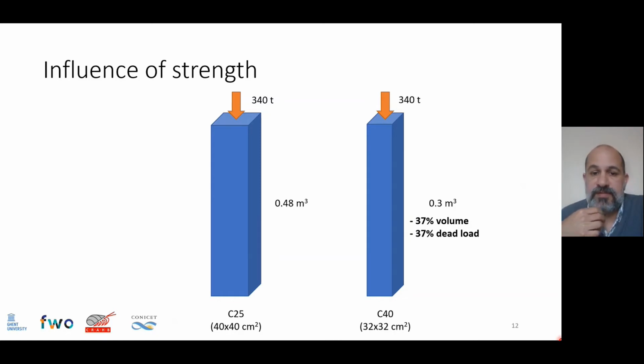So let's take this example, a column made with concrete with strength class 25 megapascals. We would need half a cubic meter to resist 340 tons. But if we increase to 40 megapascals, we can reduce the volume of the column 37% and also the dead load 37%.